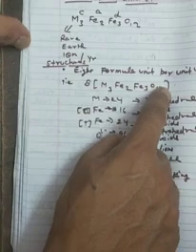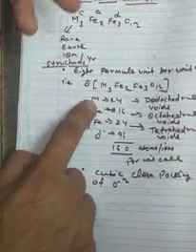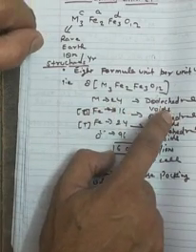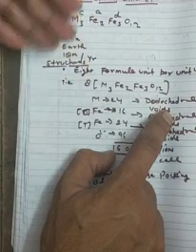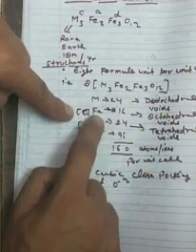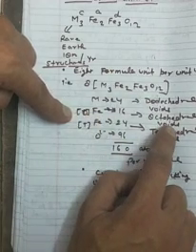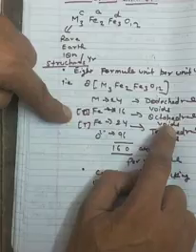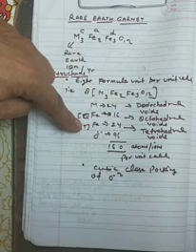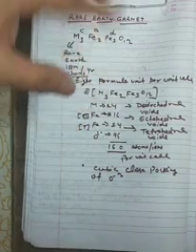I already explained this. So there will be 24 rare earth or yttrium ions, and they will fill the dodecahedral sites. They are dodecahedrally coordinated. There are 16 Fe in 3 plus state, octahedrally coordinated, and there are 24 Fe in 3 plus state, tetrahedrally coordinated.